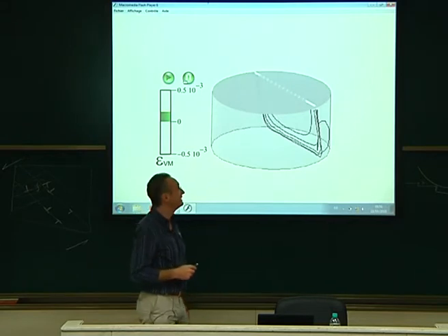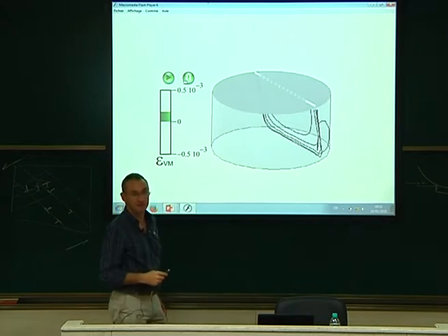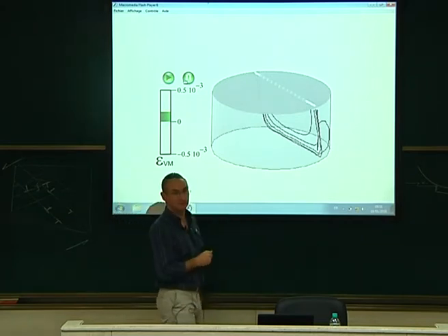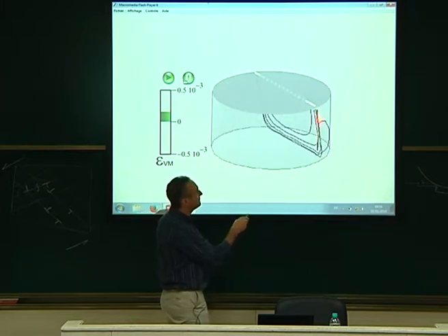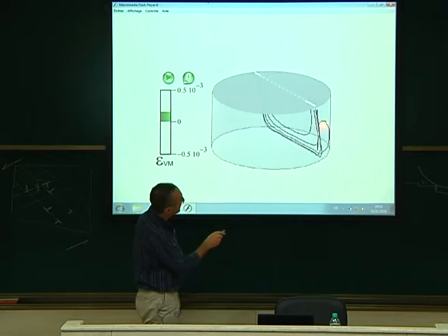It is edge, right? Why? Because the plastic steps you clearly see at the surface are like that, and the dislocation line was like this, so they are more or less perpendicular. Well, they are exactly perpendicular. So this is an edge segment, okay? So what are those segments here? Those are screw, collinear to the Burgers vector. And what do you see here?